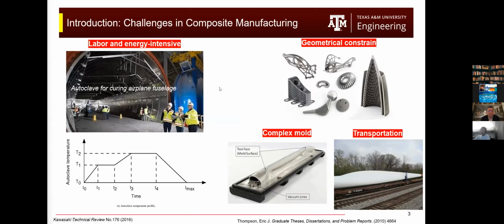So, for example, if people in the industry want to manufacture a very large piece like an airplane fuselage, they have to use an extremely large autoclave for curing, and the curing process takes hours, and a very sophisticated temperature profile has to be used here. And besides that, the shape of the composites is very hard to manufacture into a complex structure. If people want to make it complex, they also have to make a complex mold before they can process the composite. And then after the large piece is manufactured, the transportation is also a problem.